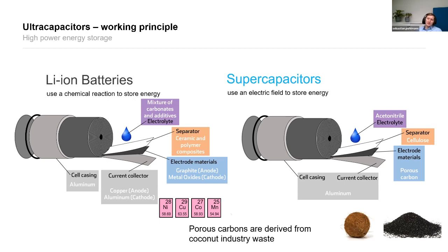However, if you then analyze the materials, then supercapacitors use fairly simple mixes of materials. So whereas in lithium-ion batteries here on the left side, you have mixtures of carbonates and additives as electrolytes, you have even composite separators, but more importantly, you have very complex electrode formulations with graphite on the anode, metal oxides on the cathode. You have different current collectors like aluminum on one side, copper on the other side. And you have a lot of different materials in there like nickel, copper, cobalt, or manganese.